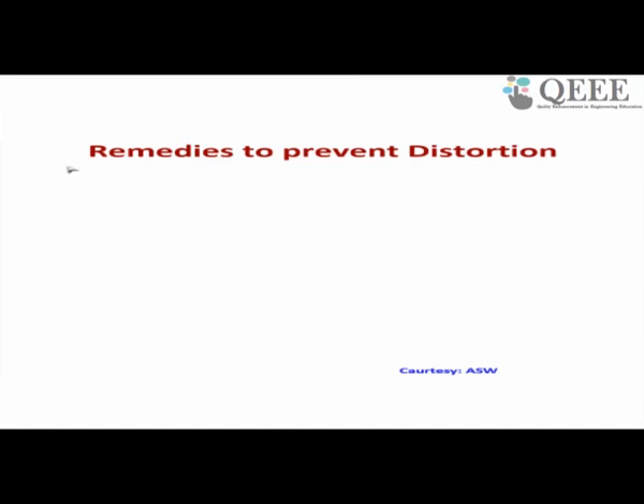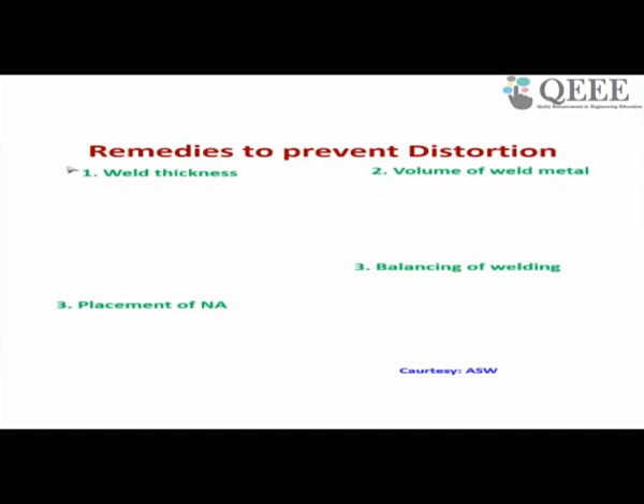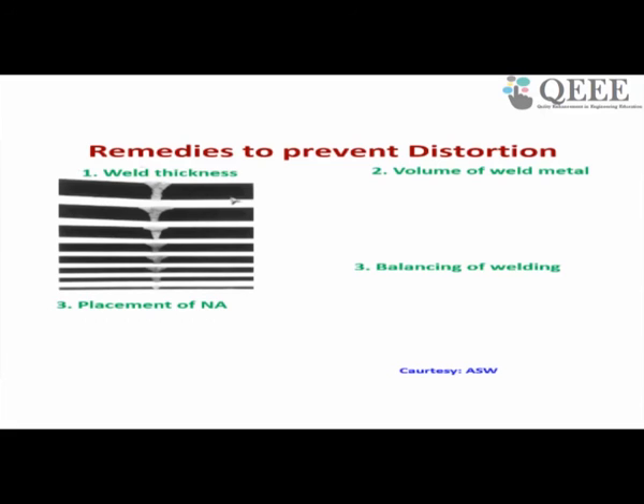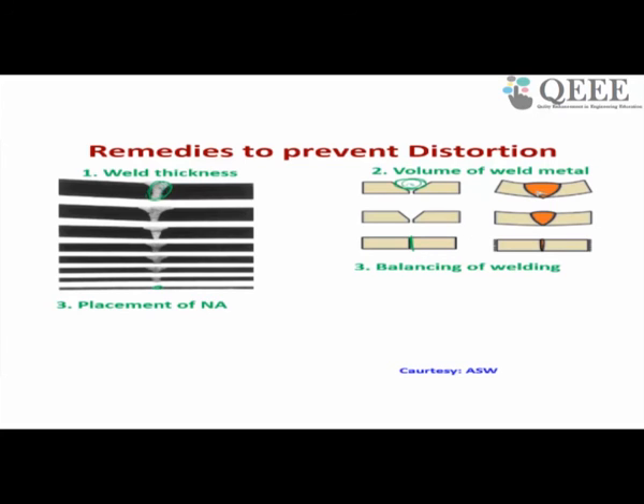How to prevent distortion? By doing proper design, joint design, you can prevent distortion. For example, by providing proper joint thickness. For thick material, distortion will be very high because heat input in this zone will be very high, because your metal is thick, more filler metal is required, so more heat input, so it will distort in a significant way. For thin material, less filler metal will be required, so less heat input, so there will be a smaller fraction of distortion. Similarly, if the volume of material is more, more material is required to be placed here, so distortion will be more here. Here a lesser volume is required to be joined, so distortion will be less here, you can see.